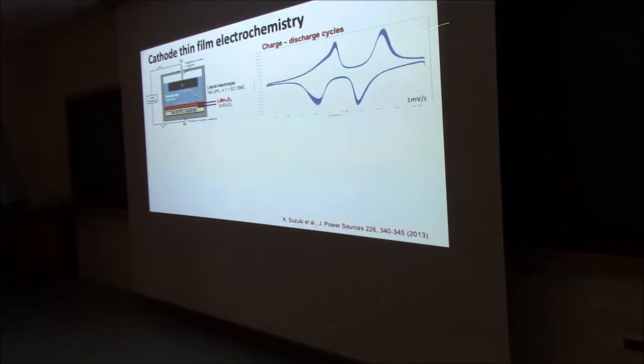And then you have this picture, where you can see at specific voltages, you can see a peak. So if you go here from a low voltage to a higher voltage, this is during charging. This is the first peak. That's where the first position of lithium is taken out. This is the second, like this. So this is the second. And on the way back, you fill it back up. You go from this phase to this phase. No lithium, because you can take out 100% of lithium in this case.